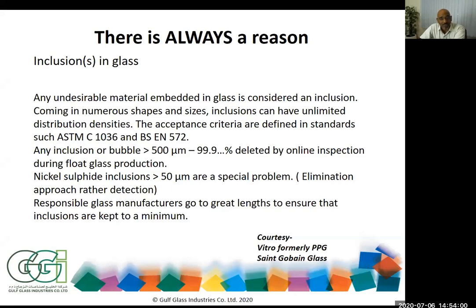There are inclusions which are allowed in the glass of 0.3 mm, even up to 0.5 mm. Having said that, any inclusion or bubble greater than 500 microns, 99.9% is detected by the online inspection and then removed during float glass production. The issue is that nickel sulfide inclusion greater than 50 microns can create special problems. Detecting such inclusions is difficult on the line. No matter what people say, with detectors on the line you cannot detect such small inclusions very easily. And so an elimination approach is better.